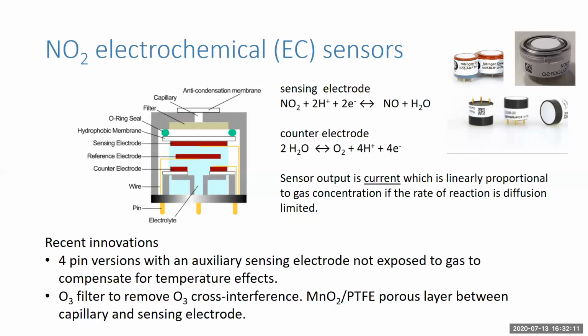In the case of NO2, NO2 is reduced to NO, and simultaneously at the counter electrode there is the oxidation of water reaction. As I said, the output of the cell is a small current, and this is usually on the order of a few nanoamps for ppb levels of NO2. There's been a number of recent innovations. The first is a 4-pin version with an extra electrode called an auxiliary electrode that's not exposed to the gas, and this is used to compensate various temperature and perhaps humidity effects.